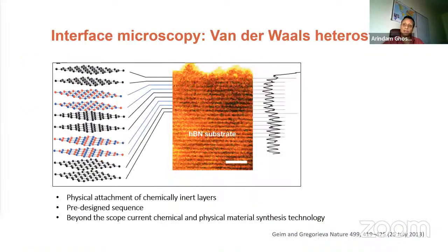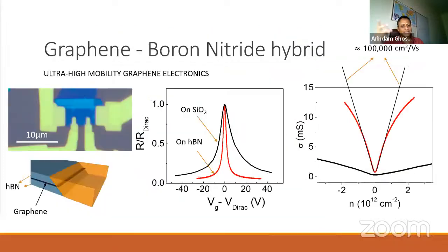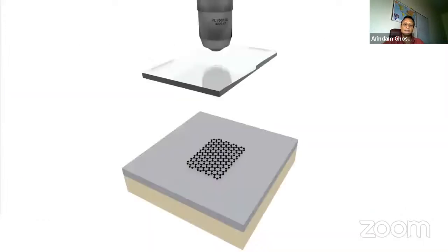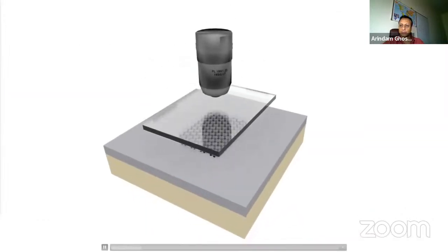And these have extremely good quality interfaces. There's no doubt this atomically clean interface leads to very interesting new physics. But as I said, van der Waals heterostructures were there before we started, but at that point of time, people were using them for improving the quality of the material. For example, by putting graphene between 2 layers of boron nitride, a very high mobility was obtained, as I showed you earlier. But what we did for the first time, we put, as I said, graphene on molybdenum disulfide.